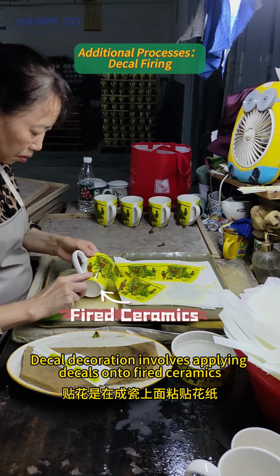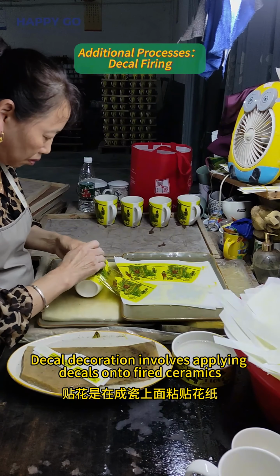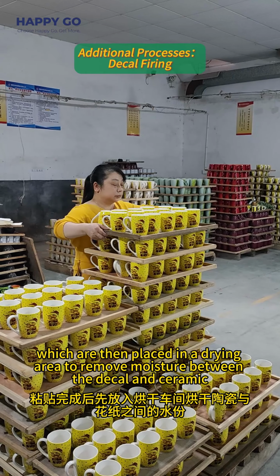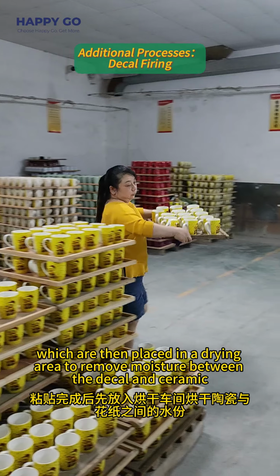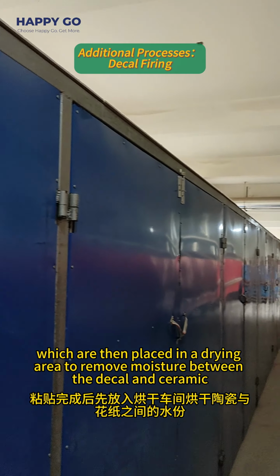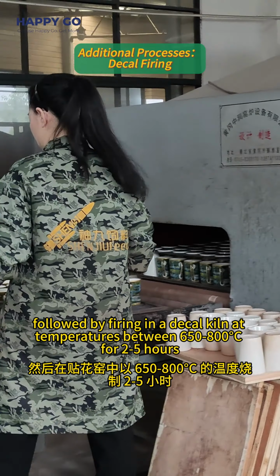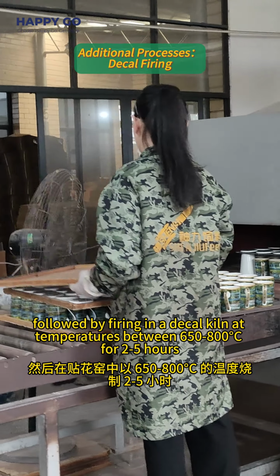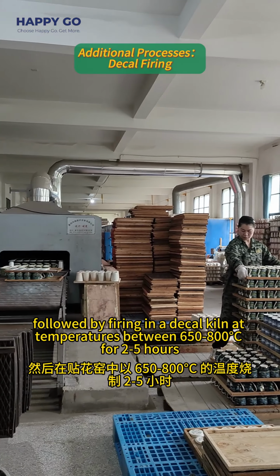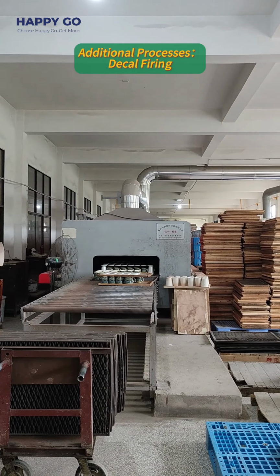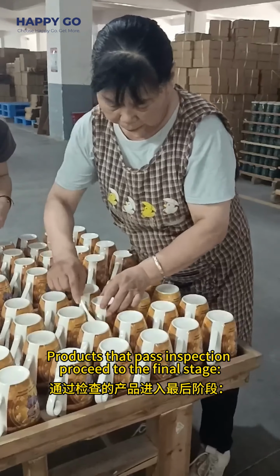Decal decoration involves applying decals onto fired ceramics, which are then placed in a drying area to remove moisture between the decals and ceramics, followed by firing in a decal kiln at temperatures between 650 to 800 C for 2 to 5 hours. Products that pass inspection proceed to the final stage.